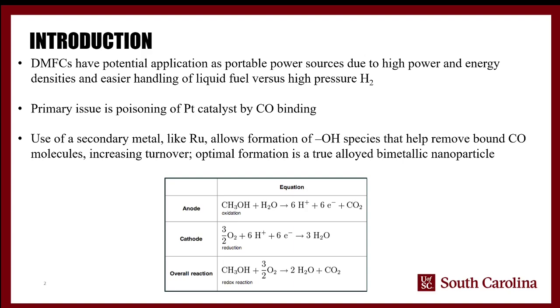And what decades of study have found is that if you have a secondary metal like ruthenium, you can actually get that secondary metal to help form OH species in a neighboring site to the CO that's bound to platinum. And those OH species actually help remove the bound CO. And so that increases your turnover by clearing out the catalyst sites. And of course, the optimal formation is a truly alloyed bimetallic particle.